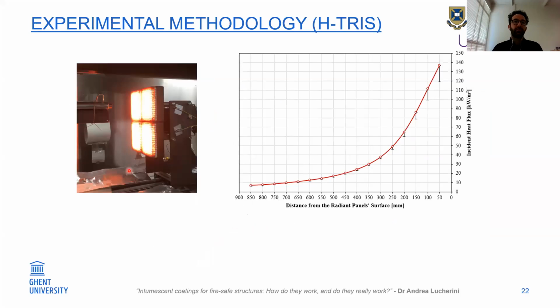Then, using a water-cooled heat flux gauge, it is possible to do a calibration of the system, correlating the distance from the radiant panel surface with the incident heat flux at different distances. For this specific system that I use in my research, you can get up to 140 kilowatt per square meter by simply controlling the distance between the radiant panel surface and the test sample.